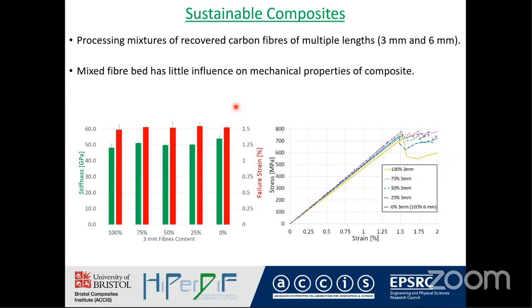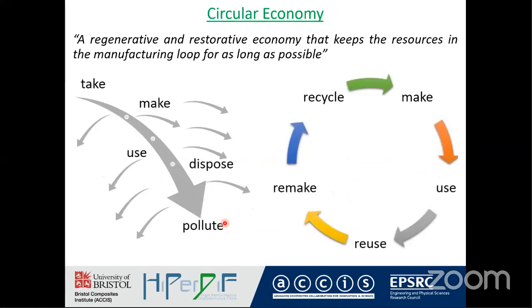As I've said previously, there's an opportunity here to improve the ability for the combination of different fiber types. And in this case, we're looking at the potential to combine carbon fibers of different lengths. So in this case, a combination of a 3mm and a 6mm fiber, again, shows that stiffness is largely unaffected as you move from 100% of the 3mm fiber through to 100% 6mm. So this is a very tolerant technique when it comes to combination of different fibers.